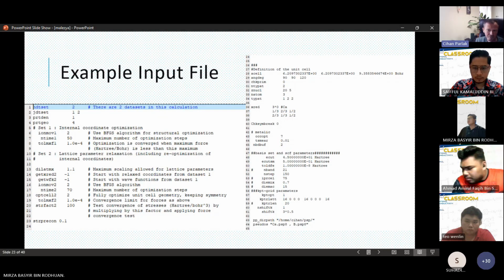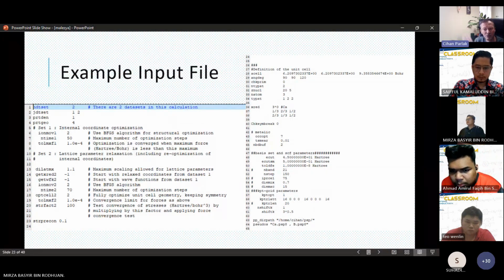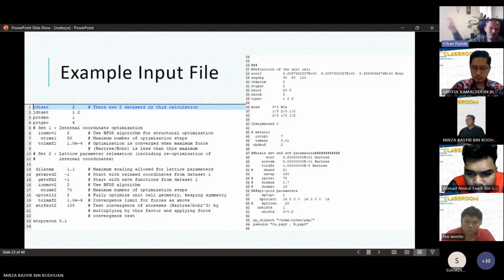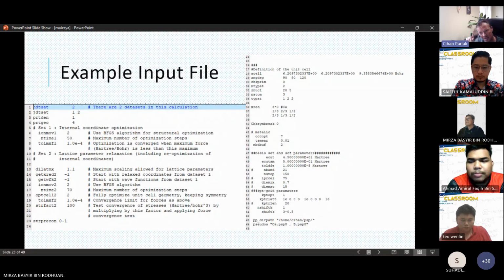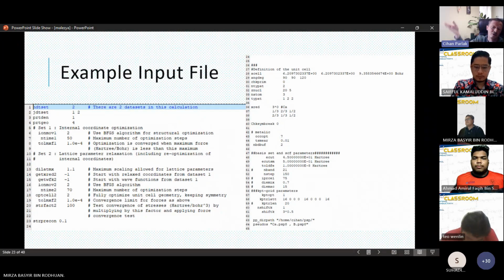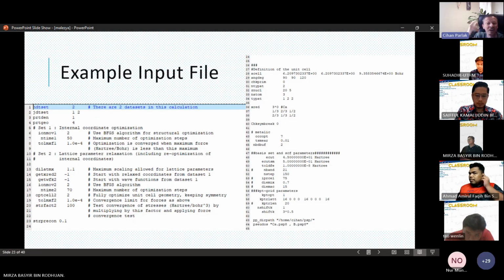We will calculate calcium diboride. It looks like magnesium diboride. I will tell you why we want to calculate calcium diboride. We give the cell parameters. This is just a suggestion for the lattice parameters A, B, and C. You can take these from experimental results, or you can just take random values, and the angles between these lattice parameters are 90, 90, and 120 to determine the hexagonal lattice.